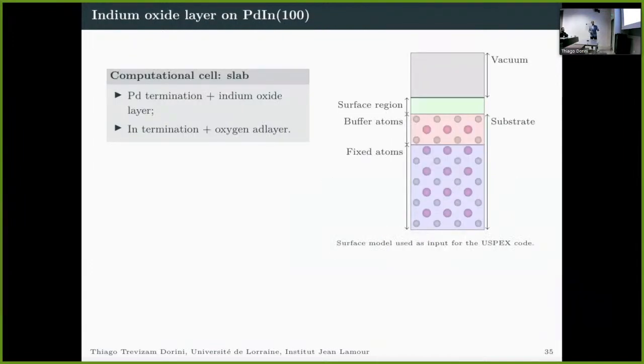To be a bit more specific, for this substrate, we have selected 2 types of terminations. First, we have fixed the palladium termination and added the indium and oxygen at the surface region. And secondly, we also fixed an indium termination and added an oxygen adlayer.